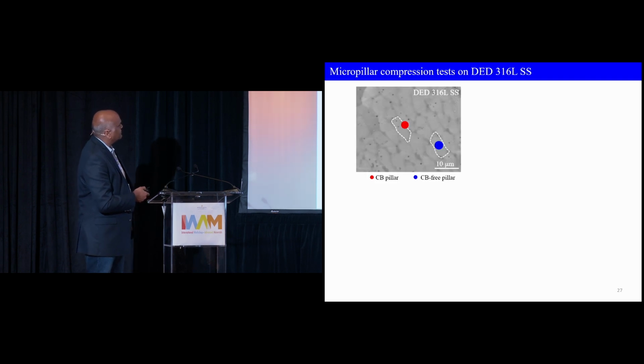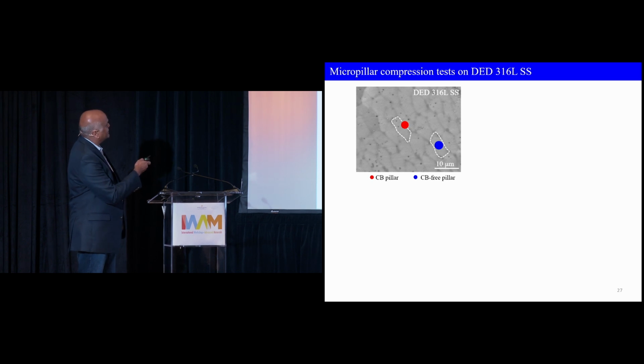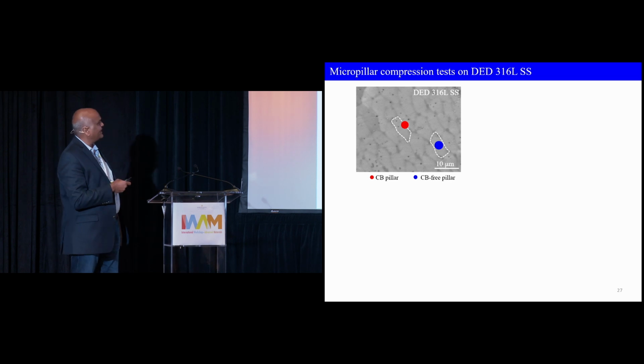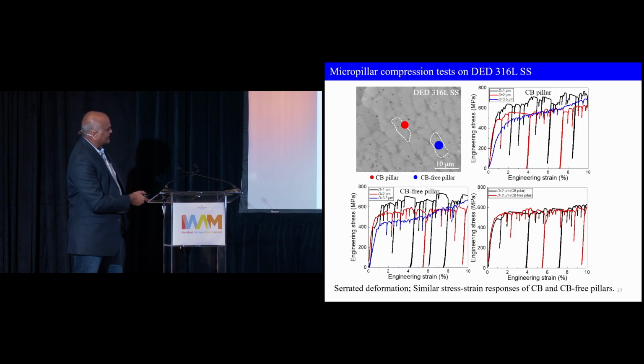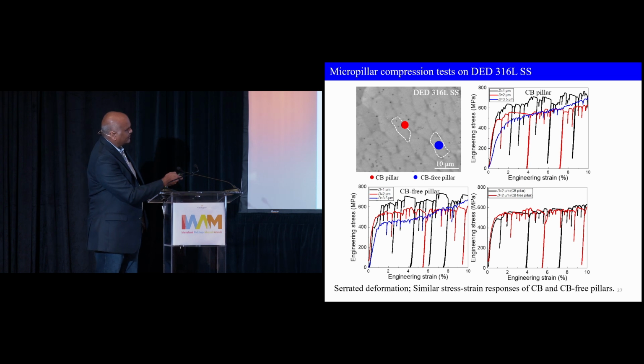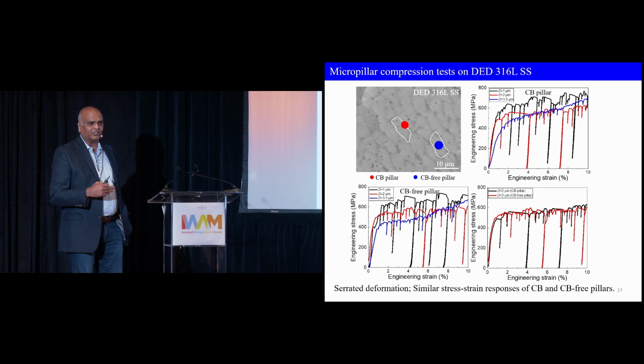Okay, so we could actually machine out pillars with or without the cellular structure, because in the directed energy deposition case, we have a fairly large cell size. We can have a pillar with a cell boundary in between, or a pillar without any boundary. So we can actually have a direct comparison of these things, and here is the comparison. So they're both 2 micron pillars, and there is no difference. So whether you have a cell boundary or not doesn't seem to be affecting the property.